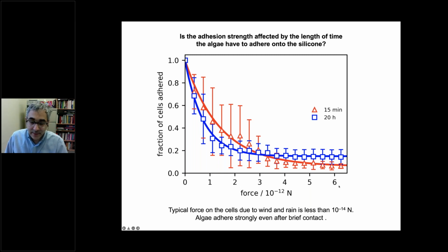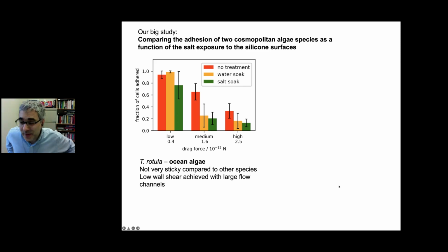But the real big study that we wanted to do, and the reason we set this up in the first place, is to do a comparison between different environmental treatments of the base of the flow cell, which is where the silicone rubber is. And what we have done is we've compared pristine silicone rubber with a silicone rubber that's been soaked in water for a month, for 30 days, before assembling it onto the bottom of the flow cell, versus a piece of silicone rubber which has been soaked in a salt water solution for 30 days before making it be the bottom of the flow cell chamber.